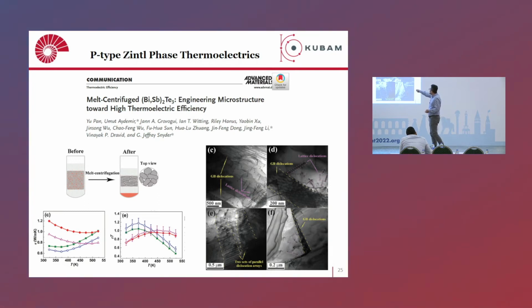We used this melt centrifugation technique on bismuth antimony telluride, which is actually the best low temperature material. So the idea is this: you intentionally add an element, for example tellurium, inside this material, bismuth antimony telluride plus some excess tellurium. And with a technique, you remove this molten tellurium at high temperature. This could be done with spark plasma sintering. What we did is we put a little bit of excess tellurium inside, put this material in an oven at high temperature, and then we quickly took it out of the oven, did the centrifugation and removed the tellurium from this phase.